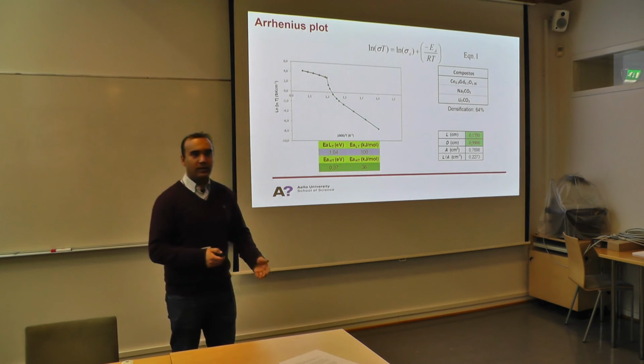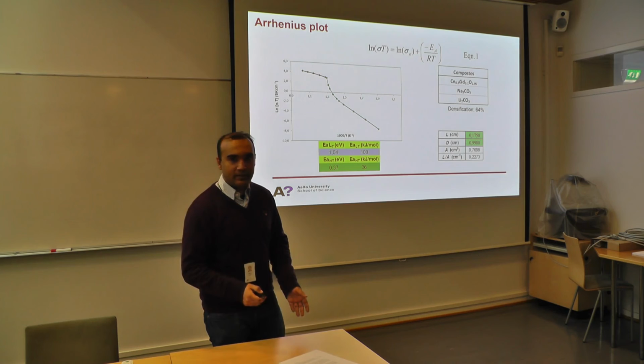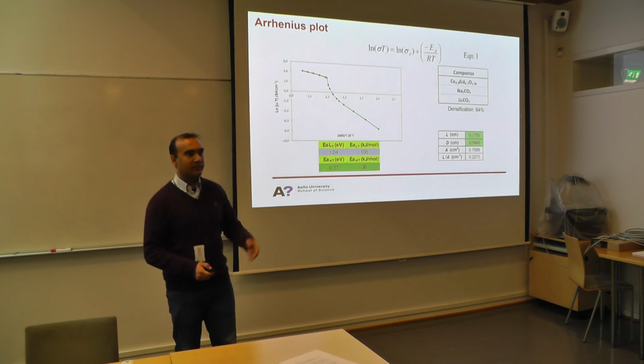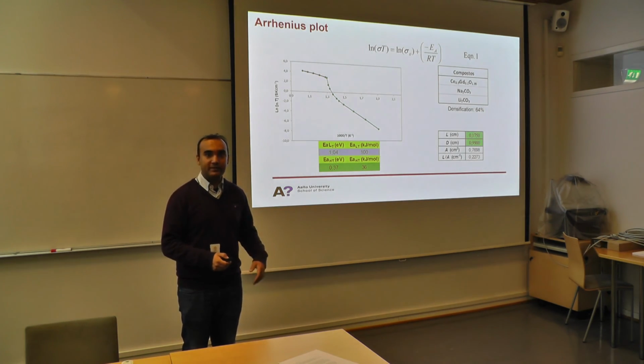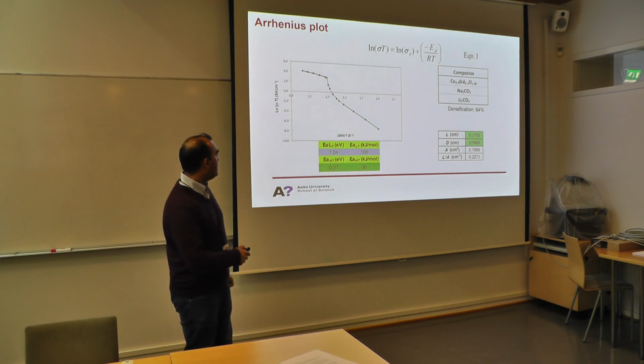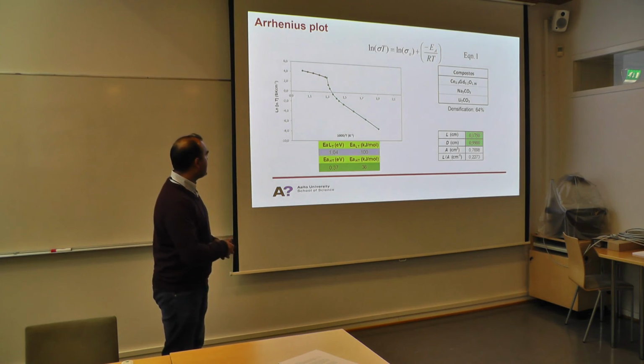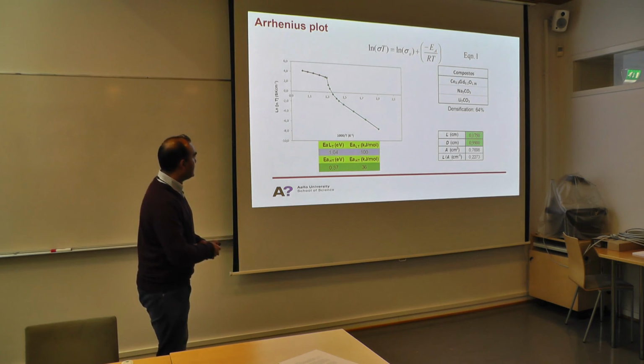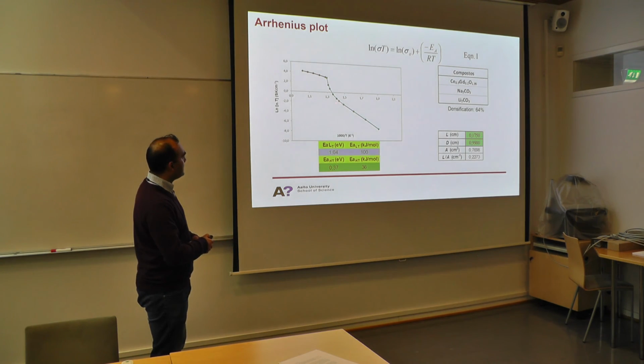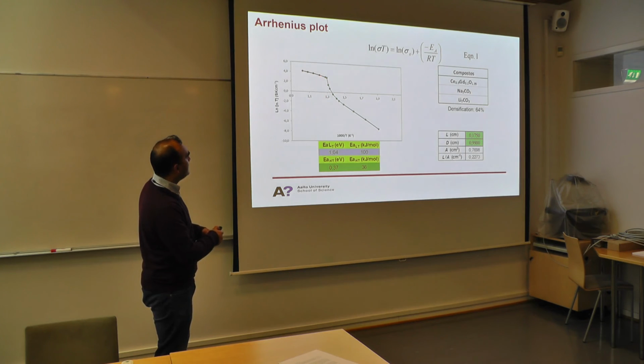And then the first thing, if we are making electrolytes, we measure its ionic conductivity with the same Arrhenius plot that we have seen, and you also have one homework on that. And here is one Arrhenius plot of a composite material. As I said, there is a straight line here, but around, I think around 400 or 500, this is the binary carbonate, so it's 500, the ionic conductivity jumps rapidly. So something happens at this point, and then at some point it starts increasing linearly again in the logarithmic scale.